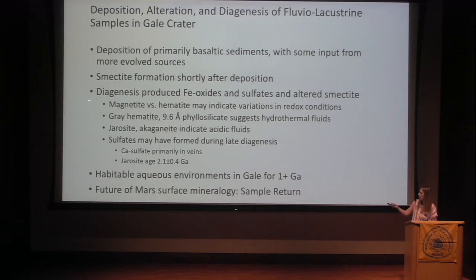The identification of magnetite versus hematite within the section indicates that some of these diagenetic fluids had variations in redox conditions. The gray hematite and ferripyrophyllite suggest that some of these diagenetic fluids were warm. The presence of jarosite and akaganeite indicates that some of these diagenetic fluids were acidic and saline. And the fact that jarosite is so young and that we see calcium sulfate primarily in veins suggests that sulfates were very late diagenetic products.